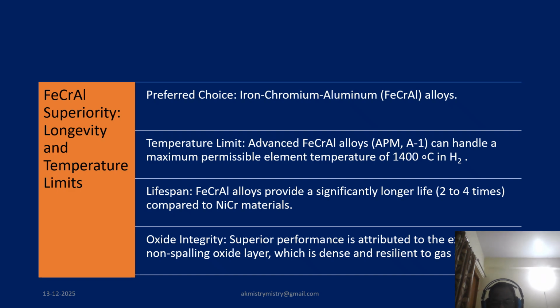ferrochromium aluminum provides a significantly longer life, 2 to 4 times compared to nickel chromium material. We have already discussed in the preceding slide that if we have contamination of any carbon monoxide, carbon dioxide and nitrogen, then we should not use nickel chromium material. We must use ferrochromium aluminum, which provides 2 to 4 times longer life, as we have just discussed. This is due to its excellent dense non-spalling oxide layer, which is resilient to gas diffusion.